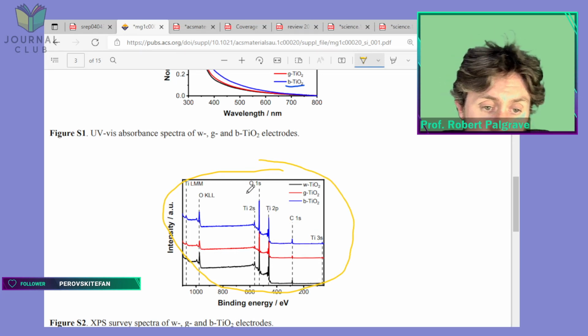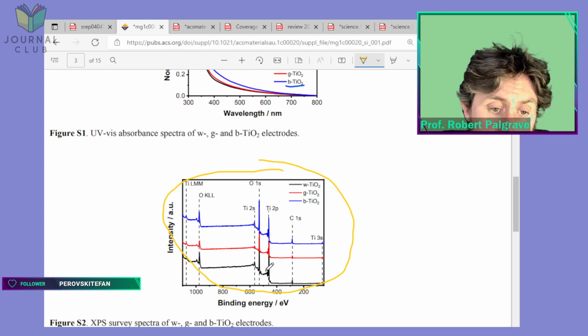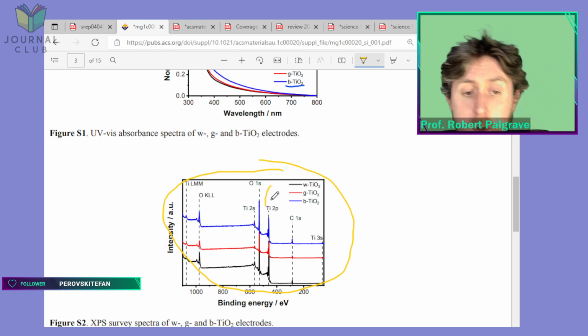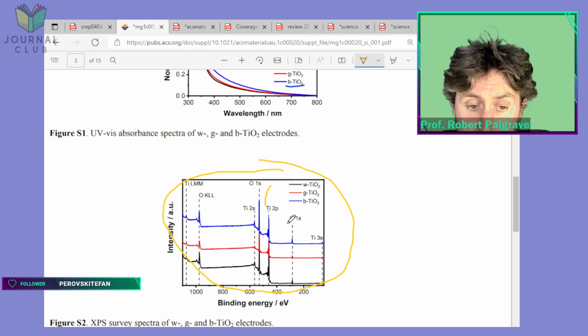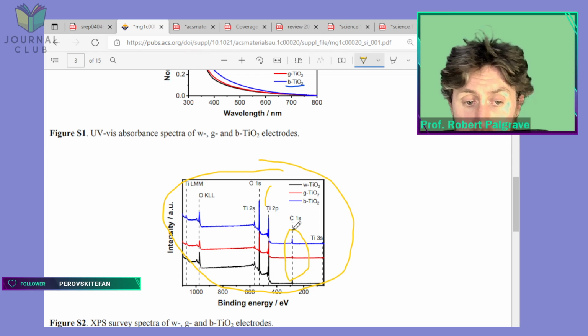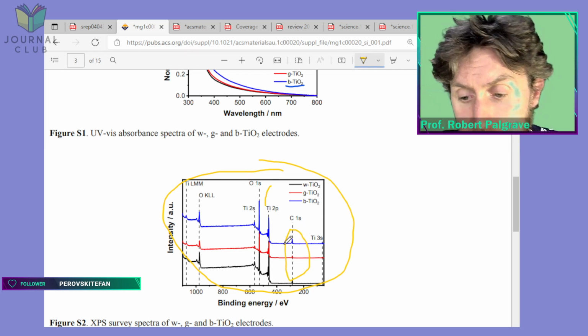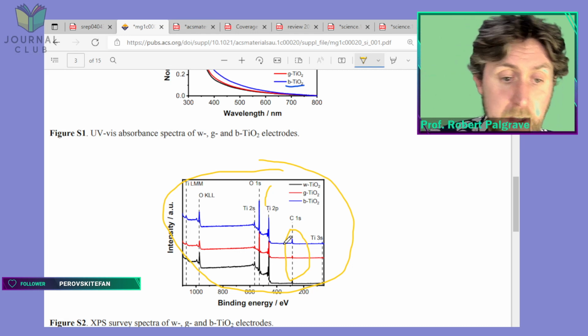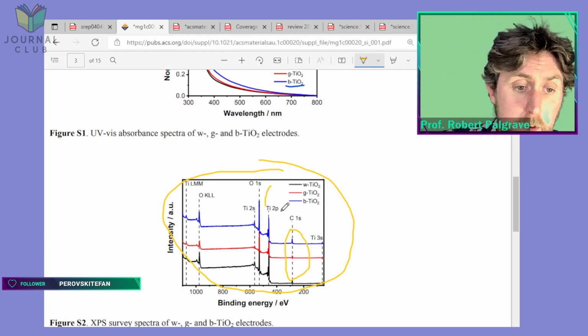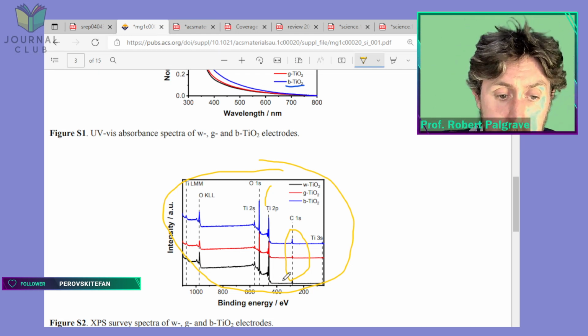So they've labelled them handily for us here. The main ones we're interested in are the titanium 2P. Of course you have TiO2, so the main non-oxygen atom is going to be titanium here. We also have some carbon here, interesting. The carbon comes from just contamination on the surface. XPS is a very surface sensitive technique, so the surface normally contains a lot of carbon just from being out in the atmosphere, and you can see that carbon here. And of course the oxygen peak here.